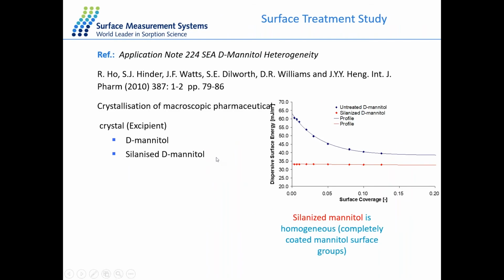I'm going to go through a few case studies, one of which is looking at analysis of D-mannitol and understanding its heterogeneity. For this example, we have D-mannitol and we have silanized D-mannitol. And this is the resulting plot that we obtain using the IGC SEA system. This is looking at the dispersive surface energy. This is a result of our non-polar probes interacting with the surface of the sample. And on the x-axis, we have surface coverage, increasing across the sample.